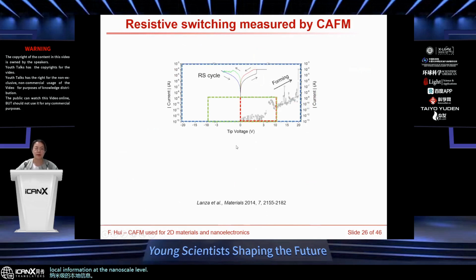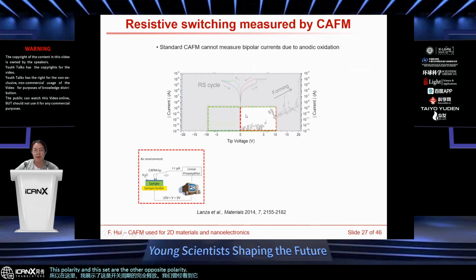So here I show the complete resistive switching cycle. We see the set on this polarity and the reset on the opposite polarity. But for the standard AFM, the main issue is that its current range and voltage range are very limited, because in this case we can only see the information in this window.